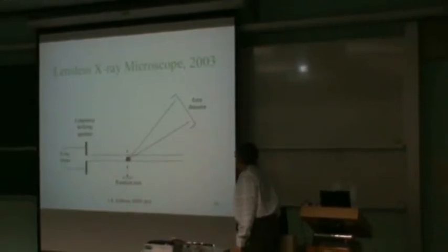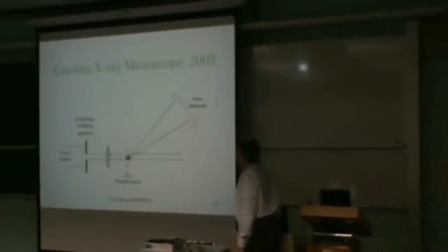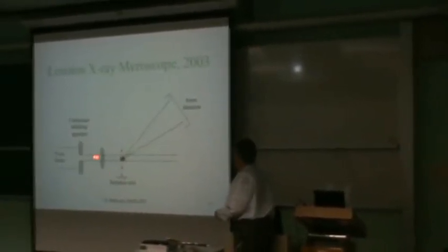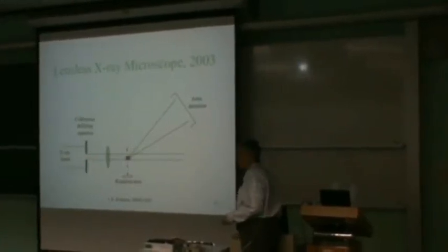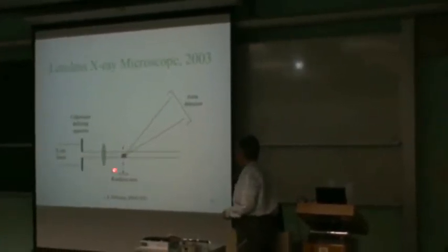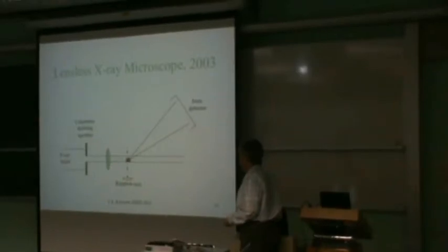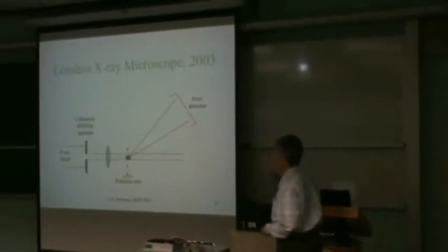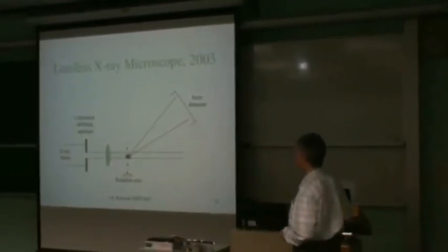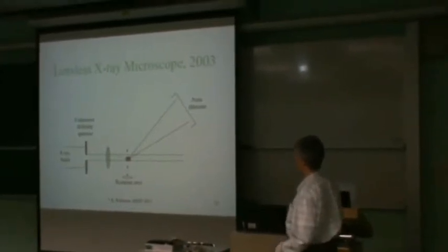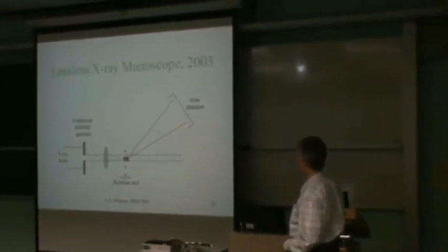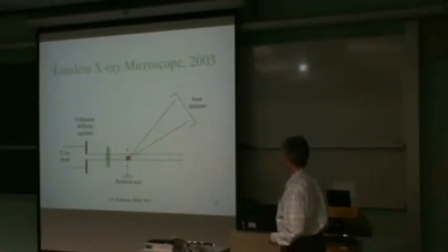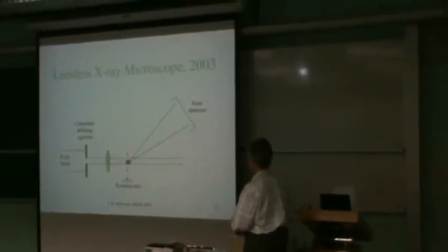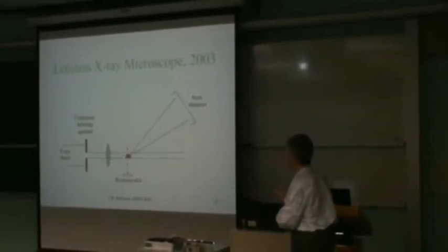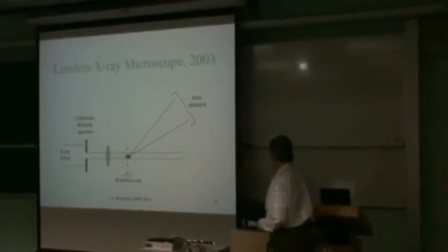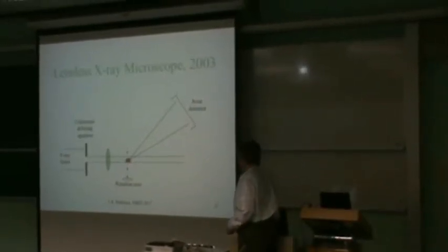We're also able to put focusing optics in, so long as we put them in after we've put the aperture to define the coherence. And that gets us down to quite high fluxes on the sample, gets us to match the size of the beam to the size of the wires or the silicon structure that we're looking at, and use that 1% of the flux fairly efficiently. But that's the only optical trick that we're using.